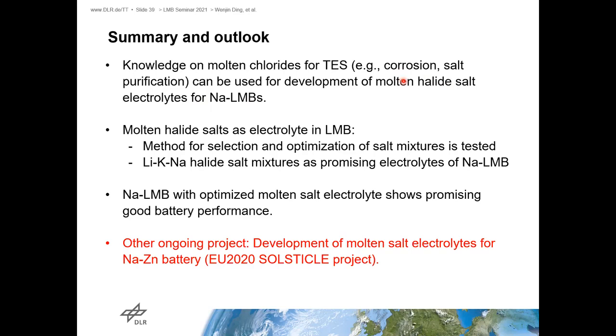We have developed a method for the selection and optimization of the salt mixtures, and it has been tested and published. The lithium, potassium, and sodium halide salt mixtures are found to be promising electrolytes for sodium liquid metal batteries. And the sodium liquid metal batteries with the optimized molten salt electrolyte show very good battery performance. It has similar battery performance to the conventional calcium-based liquid metal batteries.